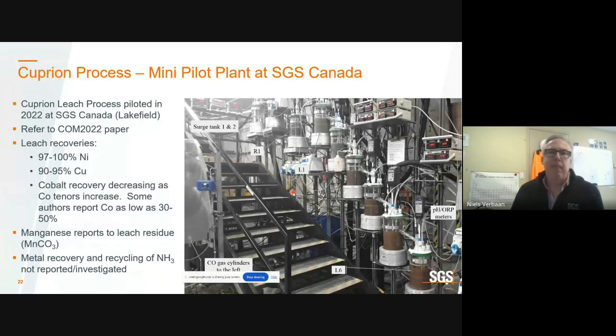Here's a picture of this pilot plant. It was a small pilot plant, used one of our mini rigs here, and we did this in 2022. It's been well published and described by Professor David Dreisinger in 2022. We learned that we can get high recoveries of nickel, kind of mid-90s for copper. And cobalt had really interesting behavior. It started off quite high, but as we built up cobalt tenors in our leach liquor, the cobalt recovery decreased. I think it got in our pilot plant as low as 60 or 70%. But some authors have reported cobalt as low as 30 to 50%.